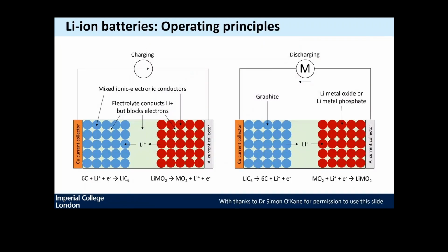Okay. And this is how it's done in the classical P2D model. We obviously have to still make a lot of assumptions, but we are aiming to write the equations that retrieve those mechanisms, and those actors that I gave you, so lithium plus and Li0, will basically become our unknowns that we are solving for. So going away from the real microstructure of the cell, we want to have this domain that is the electrodes, and we want to at least be able to retrieve two phenomena.